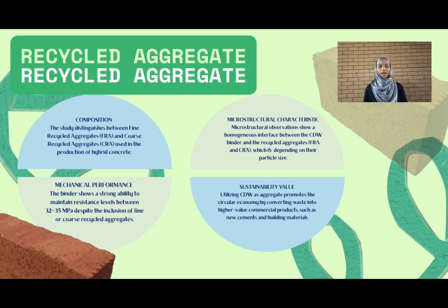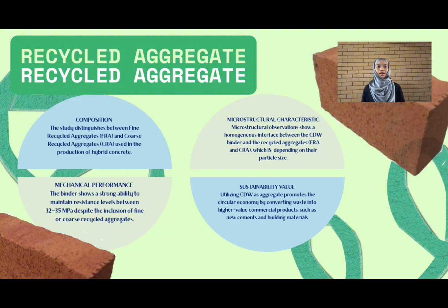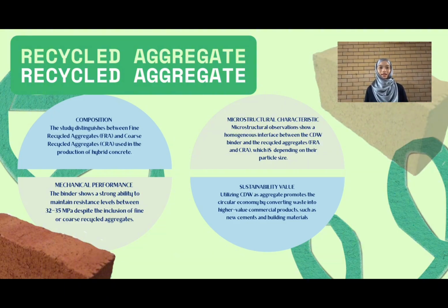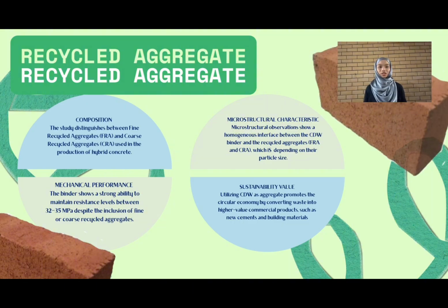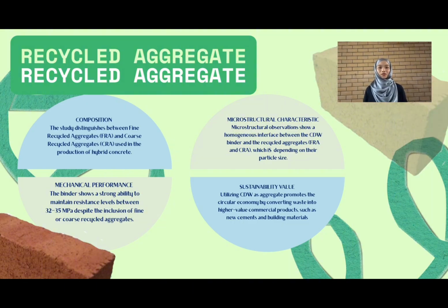Most importantly, the mechanical performance remained remarkably stable. The binder demonstrates a strong ability to maintain resistance levels between 32 and 35 MPa, even with the inclusion of recycled aggregates. This proves the material is not just sustainable but structurally viable.